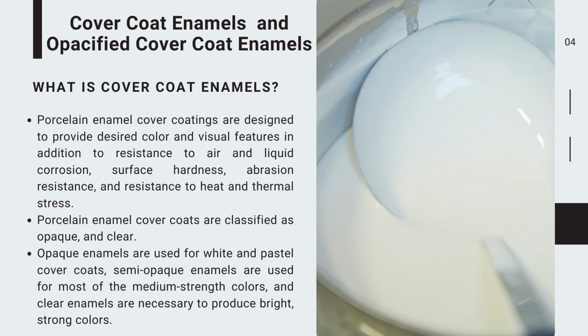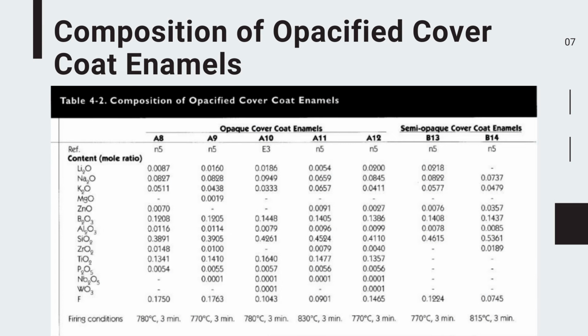Porcelain enamel cover coats are classified as opaque, semi-opaque, and clear. Opaque enamels are used for white and pastel cover coats. Semi-opaque enamels are used for most of the medium-strength colors, and clear enamels are necessary to produce bright and strong colors. Some fully opaque titania opacified porcelain enamels are given in Section A of Table 4.2. These materials have been formulated to show excellent acid resistance and, in most cases, fairly good alkaline resistance. Titania opacified enamels are produced with reflectance ranging from 78% with enamels A8 or A9 to 88% with enamel A10.